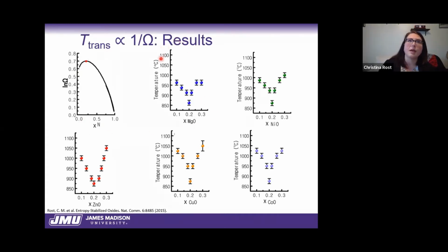And then here's my experimental system. So what I've done is I've systematically eliminated some part of each individual component plus or minus 10% off their equimolar values. And we can see that anytime I deviate from equimolar amounts, the transition temperature increases around some local minimum or global minimum, depends, under some minimum that of course happens at equimolar systems.